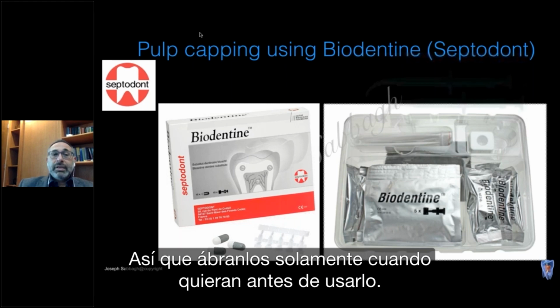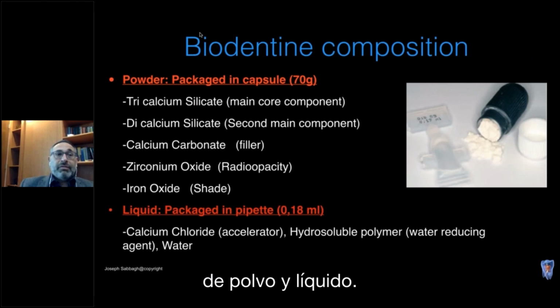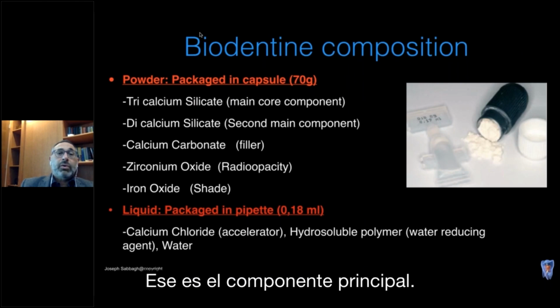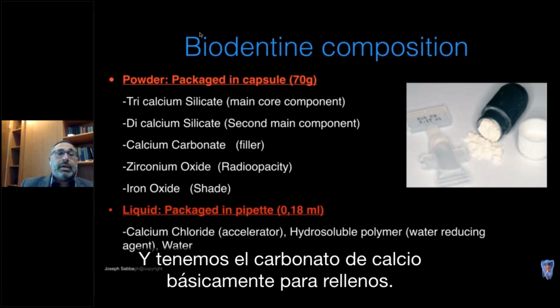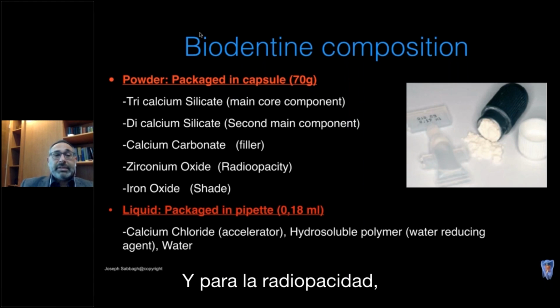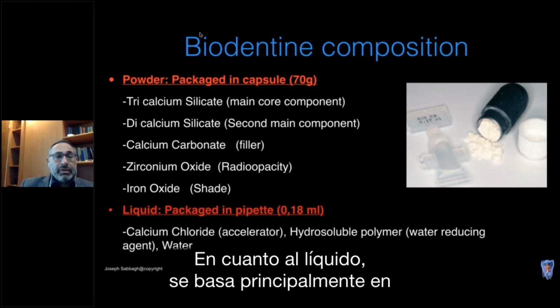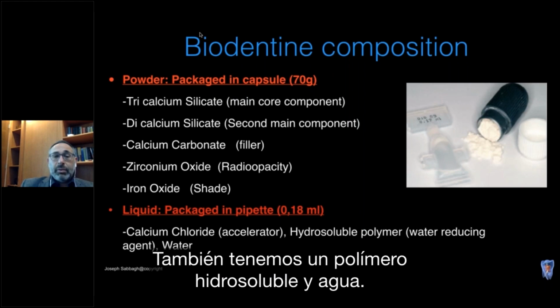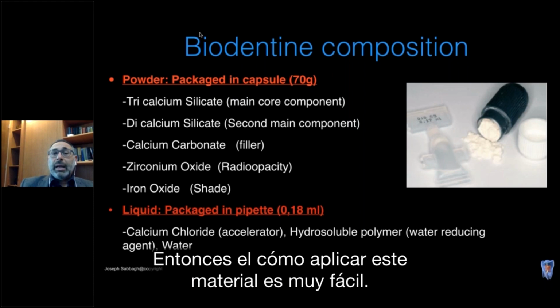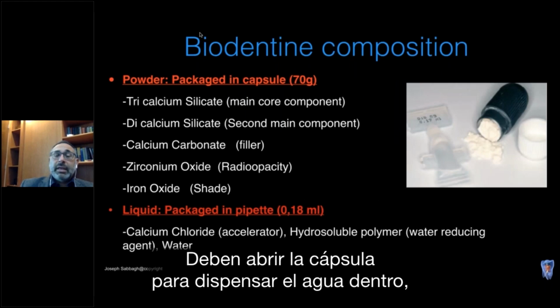So as you can see, this material is composed of a powder and liquid. The powder is mainly based on tricalcium silicate. This is the main core component. We have also the dicalcium silicate, and this is the second main component. And we have the calcium carbonate based basically on the fillers. And we have, for sake of radio opacity, the zirconium oxide and some iron oxides as well. Concerning the liquid, it is mainly based on calcium chloride that serves as an accelerator. We have also the hydrosoluble polymer and the water. So how to apply this material? It's very easy. So you need to open the capsule to dispense the water inside and to close it and put it on the vibrator. We will come to this in a few minutes.